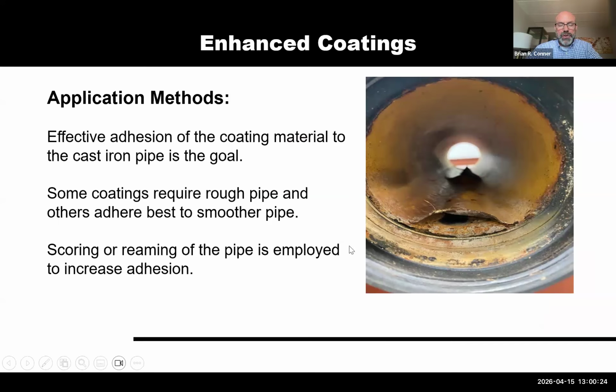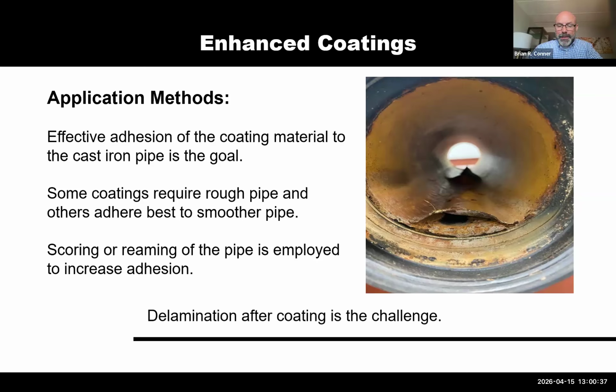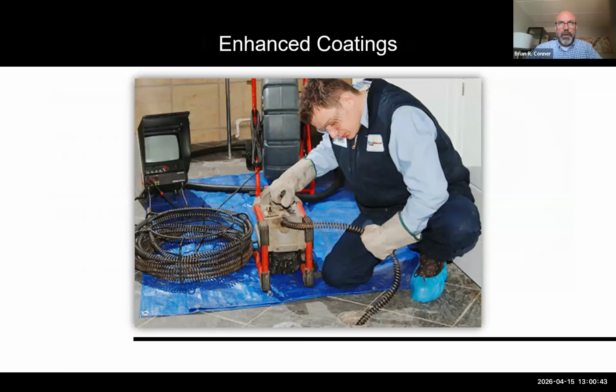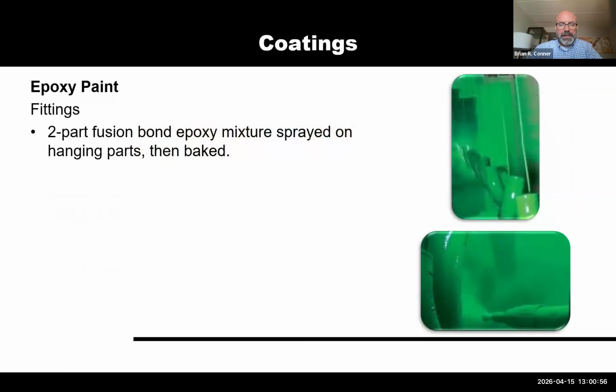So just make sure that if you're going to specify an enhanced coated cast iron, you understand which one and how it is adhered to the pipe. So delamination of the coating would be challenging for the overall health of the system. Also, because of the way some of these coatings are used, snaking the piping system out can be problematic. So again, I would just recommend that you do your due diligence if you're thinking about specifying an enhanced coated cast iron that's outside of the one that Charlotte manufactures in our Edge HP.